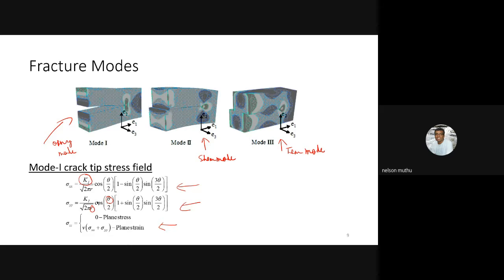Okay. So now, you are able to see the stress field sigma xx and sigma yy, and you also have tau xy as well, for mode 1. For plane stress, obviously the stress in the third direction is going to be 0. For plane strain, the stress in the third direction is going to be nu times (sigma xx plus sigma yy). Now the question is, what will be the shape of the plastic zone? You can use various criteria. The Tresca criterion has been routinely used to determine the shape of the plastic zone theoretically. In some cases, people also use the von Mises criterion. In fact, if you see carefully, in the von Mises criterion there is a clear distinction between plane stress and plane strain, and therefore it becomes very easy to represent that as well. So here I will show both the Tresca criterion as well as the von Mises criterion.